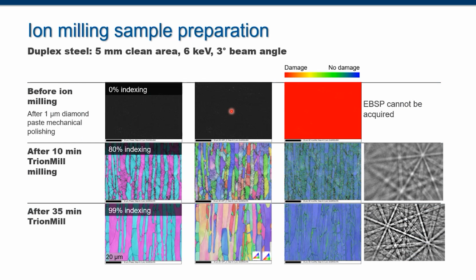So what does argon ion milling do for our sample? This is an example of an application for EBSD, which is one of the techniques that you can use to evaluate the structure of your materials. As you can see here, if you use mechanical polishing and stop, for example, at 1 micron diamond paste, you will have no indexing, no signal, nothing. You will have no EBSD patterns, so you have only damage on the surface, as described here